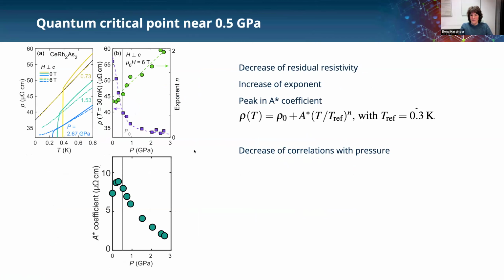Okay. So then if there's a quantum critical point, we should see this in the temperature dependence of the resistivity, and that's what we show here. So here's a pressure of 0.7 GPa, which is very close to the quantum critical point. And you can see that the resistivity is linear down to the lowest temperature we could measure. And then as we increase pressure, similar to what Stephen Hayden showed with doping, we start to develop a curvature, and the exponent grows, this is shown here in green, to around 2. So it becomes Fermi liquid-like at the highest pressures.